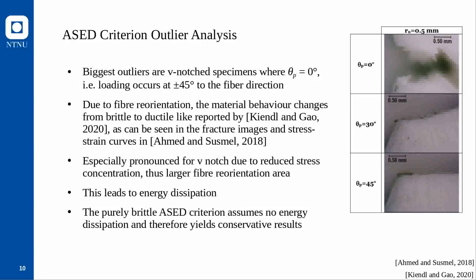This fiber reorientation phenomenon is especially pronounced for V-notches because the stress concentration factor is very low. In the analyzed data, the V-notches had very large opening angles, so the stress concentration was not high and the zone of fiber reorientation was much larger. Fiber reorientation is energy dissipation, and the ASED criterion, being an energy-based but brittle criterion, assumes no energy dissipation — all energy goes into crack formation and failure. Therefore, with significant fiber reorientation present, the ASED criterion yields conservative results.